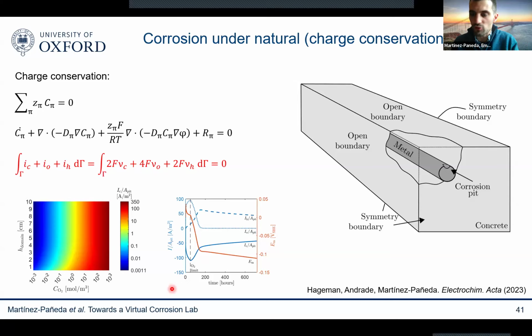So in lab conditions, we enforce an applied potential, an applied current, but in natural conditions, you have charge conservation. Your metal is degrading without any applied potential. So basically, you can do that. You can add as a degree of freedom the metal potential, and then you enforce charge conservation. This is a code that we developed in MATLAB, and we also have it in C++.